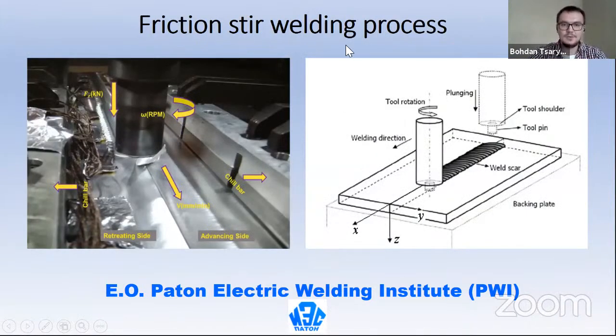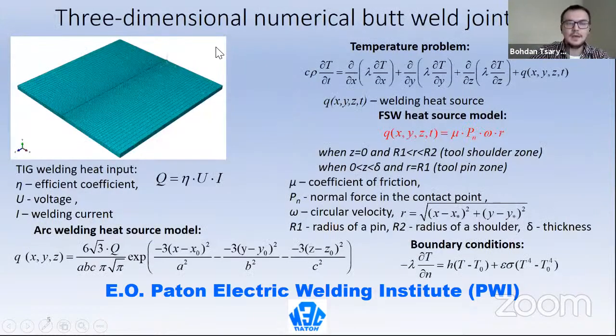During FSW, the friction stir welding process, the working tool is immersed in the metal of the welded joint, rotates and moves along the joint. Friction force generates heat, and that's why we have the joint. Here we have the numerical model for friction stir welding of a butt weld.